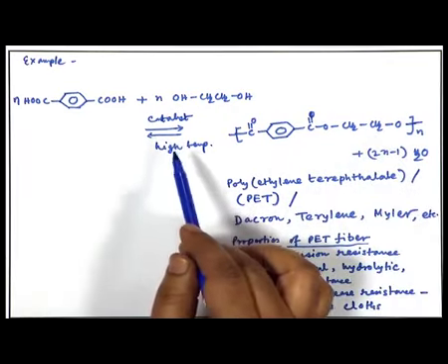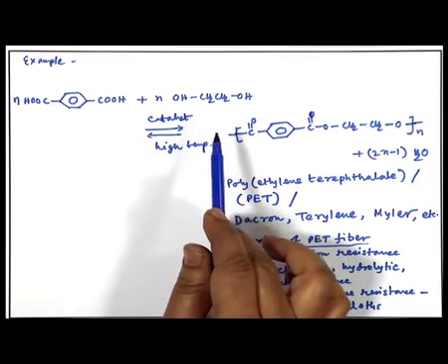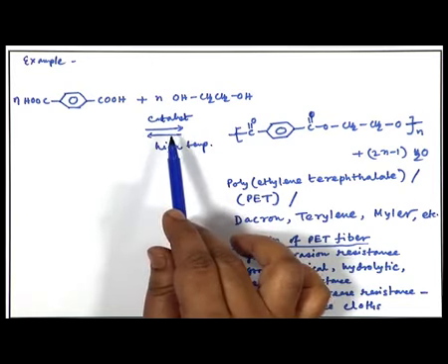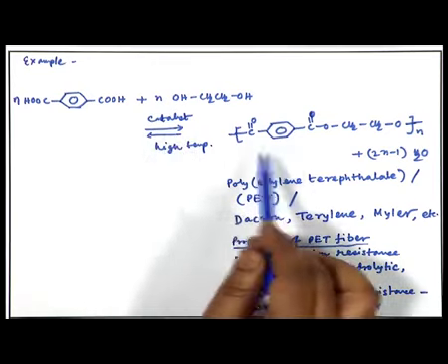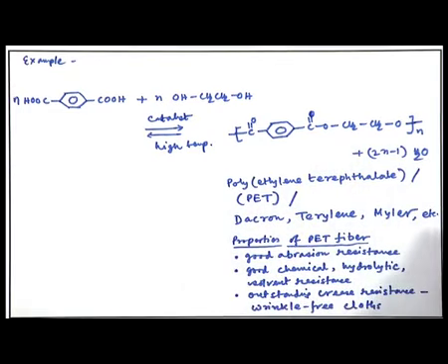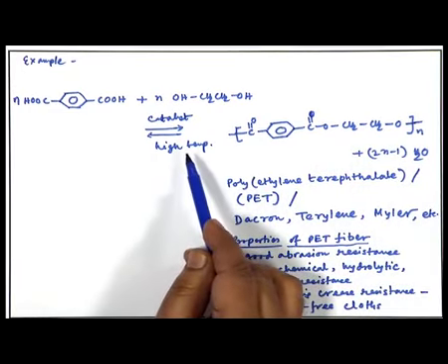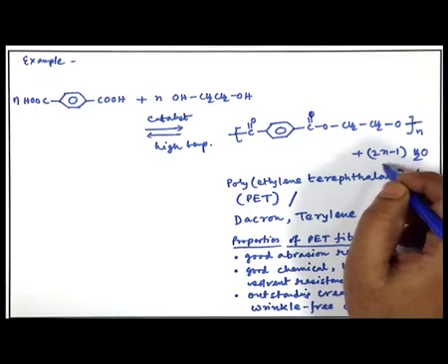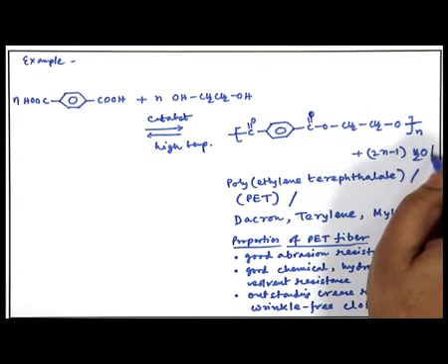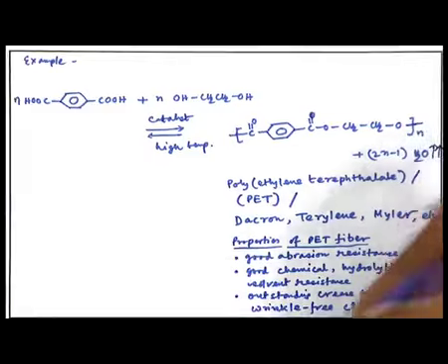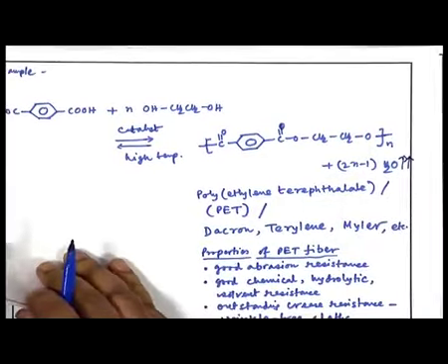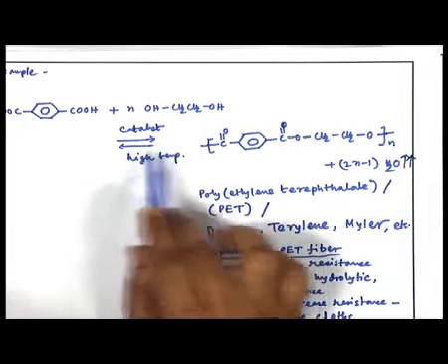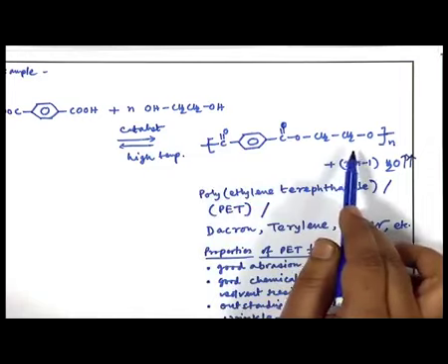Now, unlike the polyamides, this reaction is not very fast or very feasible; actually it is a reversible reaction. So, to get this polyester to form effectively, you have to increase the temperature so the reaction happens fast, and we also have to apply low pressure or vacuum and take out the water from the system, so that the equilibrium of the reversible reaction proceeds toward the product side.